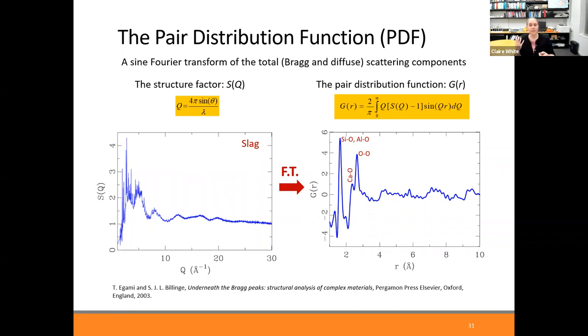And so for something that's predominantly amorphous, which is the case here, a calcium aluminosilicate glass, you've got your bond lengths, and then you end up with some medium range ordering. But once you go out to large distances between atoms, there's no ordering. And so you'll just have the data sitting at around 0.